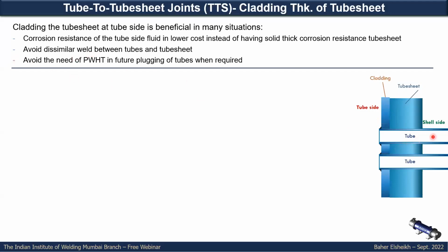In some other cases, it is also to avoid a dissimilar-metal weld between the tube and the tube sheet. If you have matching material from the cladding layer or weld overlay layer with the tube, you avoid the issue of the dissimilar weld, which can cause some cracking under thermal expansion, or also avoid galvanic corrosion. In some cases, we apply the weld overlay so that in future, whenever we need to apply plugging and the plug needs to be welded to the face of the tube sheet, you will not require heat treatment. So if the base metal, for example, is chrome-moly steel, and here you applied some grade of austenitic stainless steel or nickel alloy, then in future if you need to plug, you can plug and weld to the tube sheet face easily without the need to apply post-weld heat treatment again.